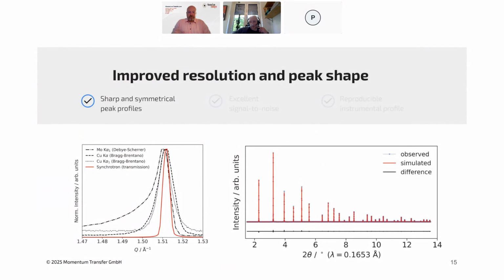And this comes from what's called axial divergence. With these systems, you typically only have a position-sensitive detector that just measures part of the diffracted signal, which is essentially a ring. And as it passes through that ring, it measures the edges for a longer period of time, and then finally passes through the outer part of the ring and essentially is not measuring anything anymore very quickly. So that's what causes this tailing towards lower angles.